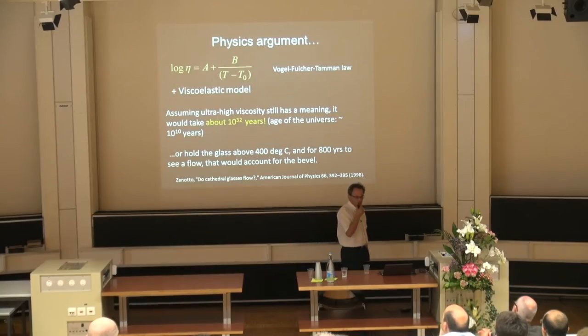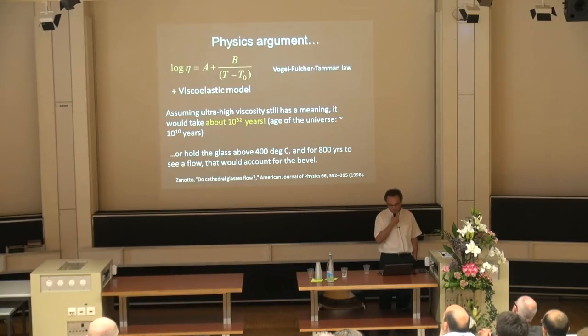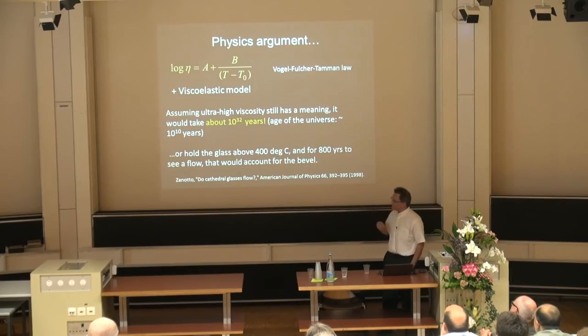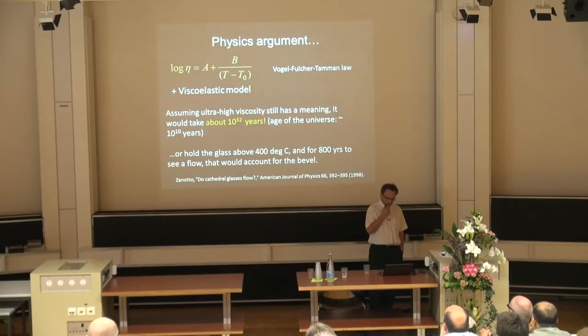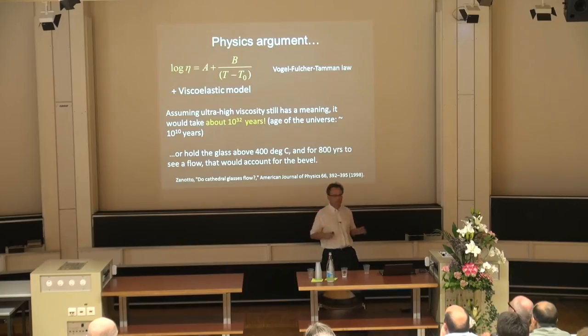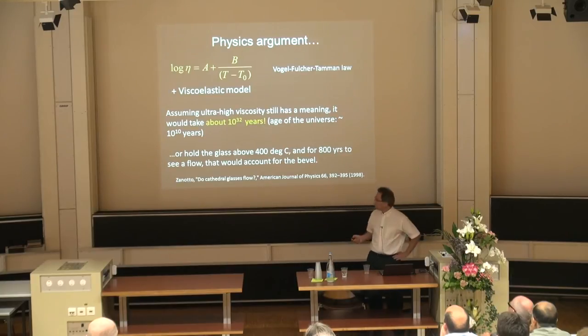So the way to model the viscosity in glass is this kind of flow, a kind of logarithmic law that you can fit for any glass, and then you couple that with a viscoelastic model. And when you do the calculations, even if you have to assume that ultra high viscosity would still have a meaning physically, but okay, let's assume that, then you find out that if you wait 10 to the power 32 years, then it may flow. Okay, so it's of course more than the age of the universe, so obviously it doesn't work.